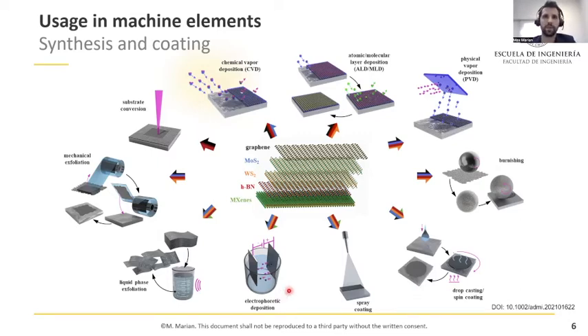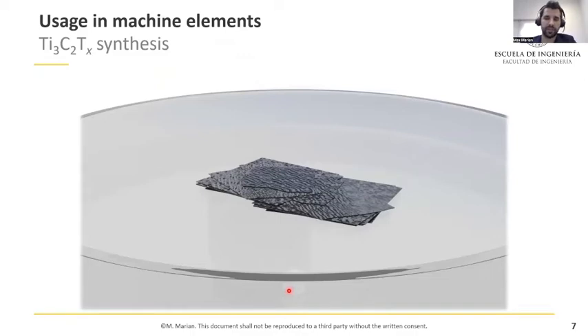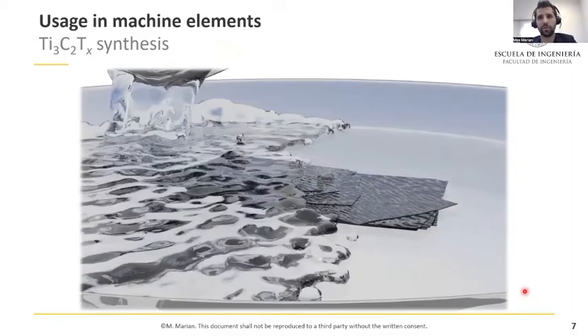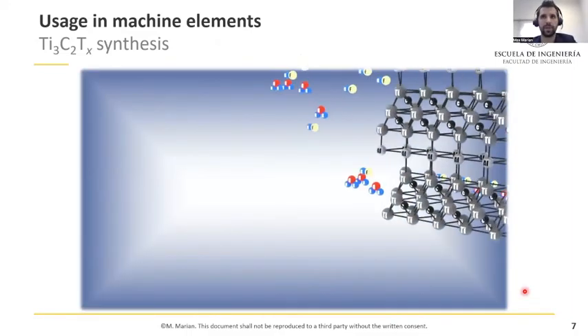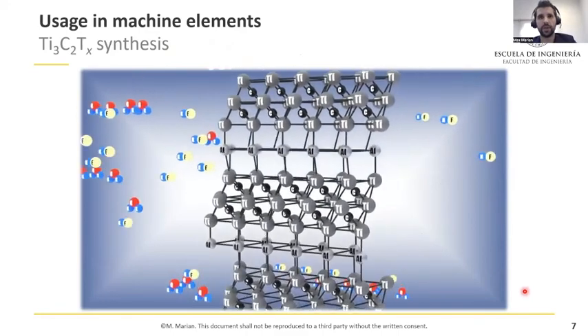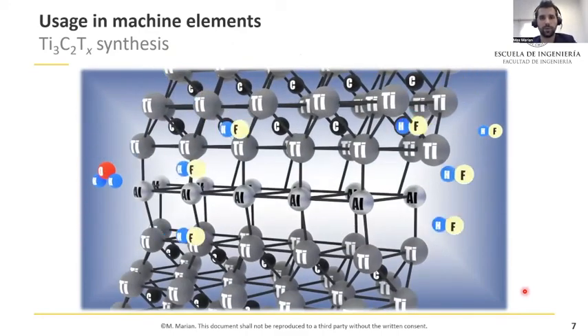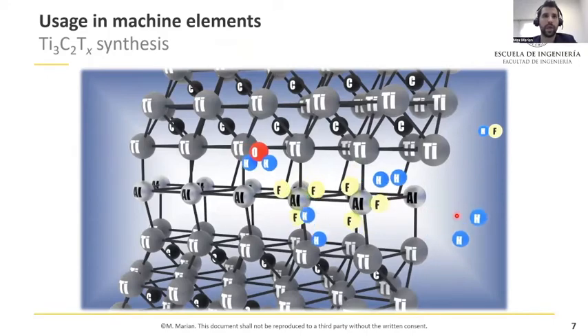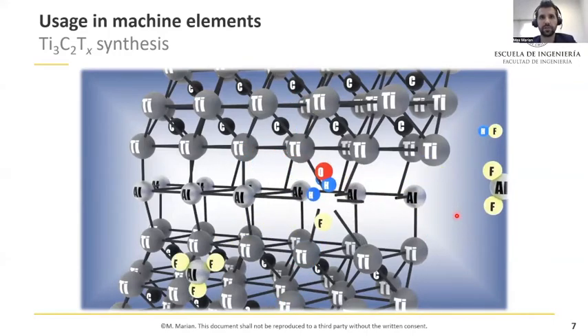So how do we synthesize the MXenes? How do we get them in a way that we can actually apply them, or, for example, drop cast them onto our component surfaces? The whole process starts with a metallic MAX phase in the form of a powder, namely layered hexagonal carbides and nitrides. In our case, titanium, aluminium, and carbon. And when we add hydrofluoric acid and mix this for some time,